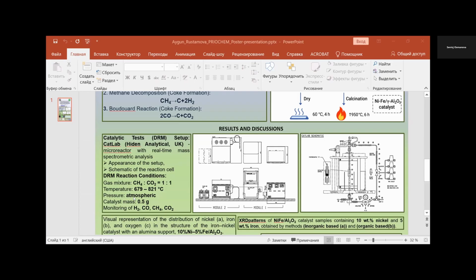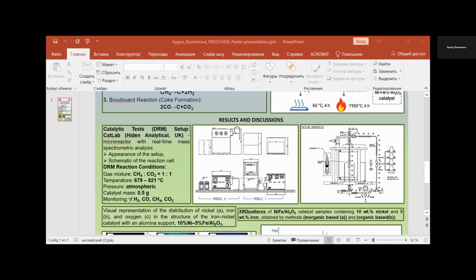make a test under conditions of temperature around 680 degrees Celsius, even more than that, and atmospheric pressure. The catalyst mass used in the test is around half a gram, and in the results part,